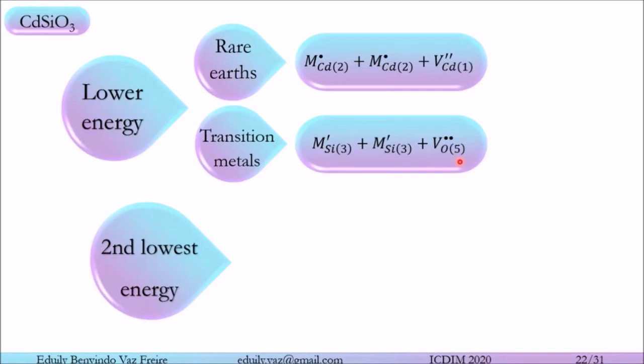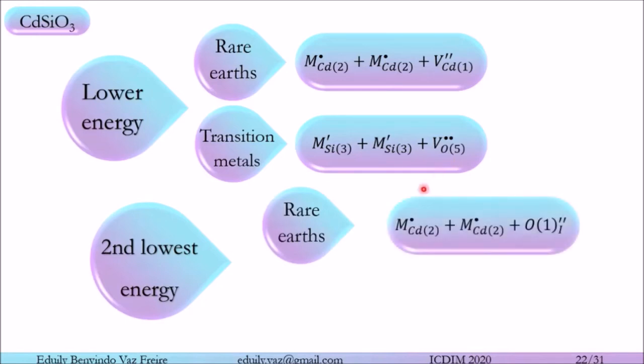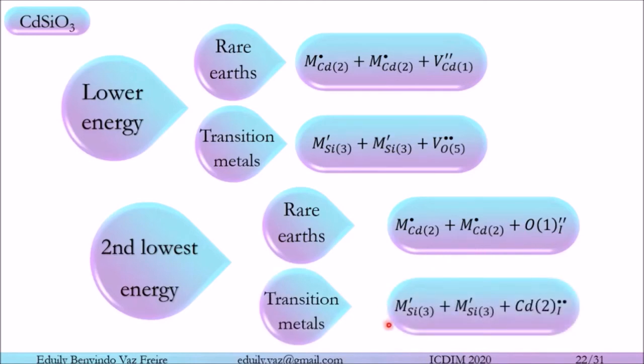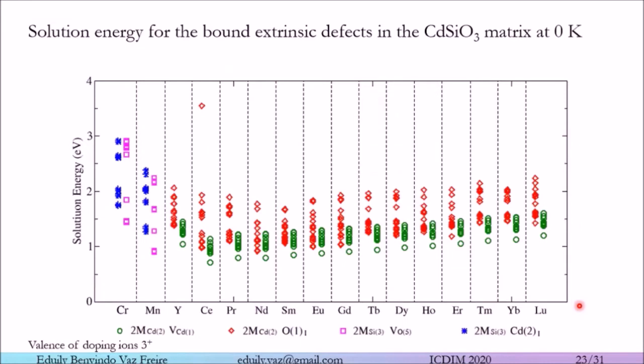This is for both temperatures. For the second lowest energy, in rare earths, it is with doping ions at cadmium 2 sites plus an interstitial oxygen 1. And for the transition metals, we have the doping ions at the silicon 3 sites plus an interstitial cadmium 2. Okay?